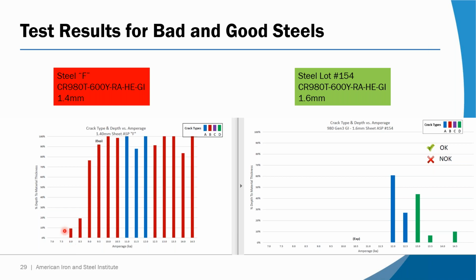So this first one, we looked at this weld at 8.0, and it was about 10% of the material thickness. Then when we went up 500 amps, now it's 20% of the way through the thickness. At 9 kiloamps, it's 75% of the way through the thickness, and on and on. Once it gets to full thickness, that's all it can be.